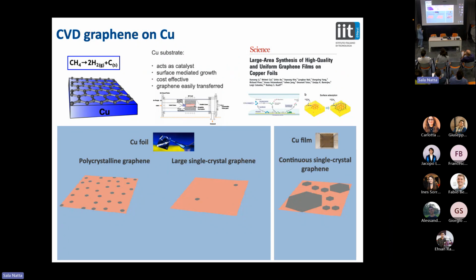We started to grow on copper foil because people saw that it was a cheap and easy way to do it. So it's a very similar foil to the one that you have in kitchen with aluminum. Yeah, it's really similar. It's nothing fancy. Then you start growing. These foils are polycrystalline. That means there are different crystal orientation. They're not oriented. So you will have polycrystalline graphene. That will mean hexagons, because graphene beautifully grows as an hexagon.